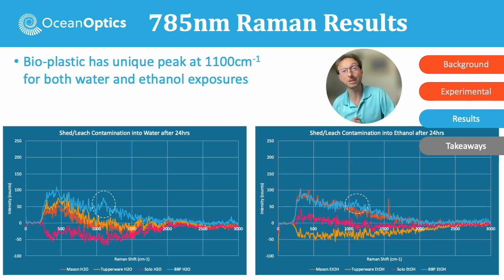Now, the bioplastic also had a unique peak in both the water and the ethanol when we ran the 785 nanometer Raman scans. So we were getting right around 1100 wave numbers. So this is in Raman shifts, which is wave numbers, not wavelength in nanometers. But right here we see it in the water and the ethanol, and it's actually more pronounced in the water, which is a little unexpected because ethanol does tend to pull things out more efficiently. So this was kind of a unique observation.